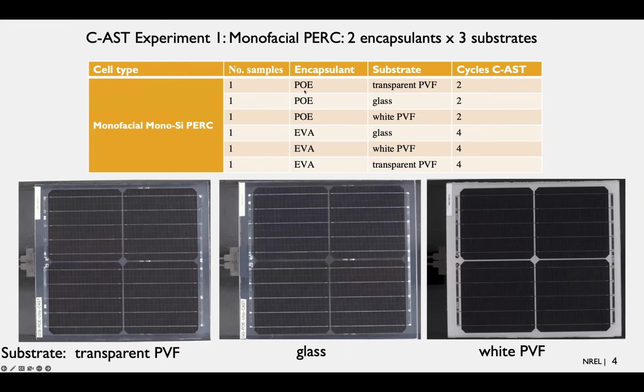The encapsulant was POE and EVA, polyolefin elastomer and ethylene vinyl acetate. And each of these had 3 different substrates: transparent PVF, glass, and a white PVF, polyvinyl fluoride that is. And the samples are shown here. They went through differing lengths of combined accelerated stress testing as shown in the rightmost column.